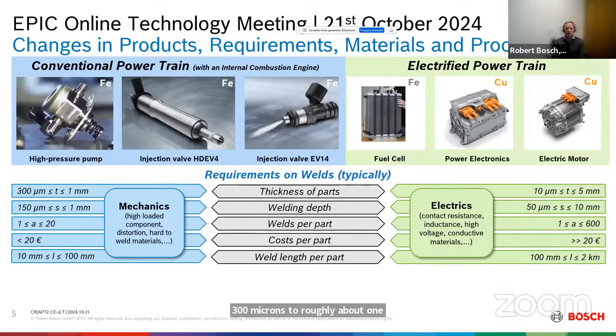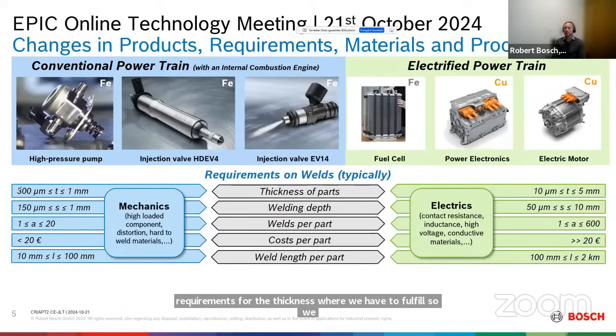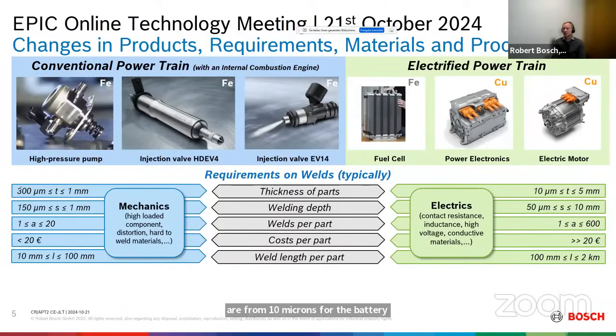This was always for injection pumps or for Bosch products, for high pressure pumps. And now we end up with a very increased range of requirements for the thickness. We go from 10 microns for the battery foils, for example, and we end up, in this case, welding copper of 5 millimeter thickness, which is really challenging using lasers. So, for example, for busbar welding for e-drives.